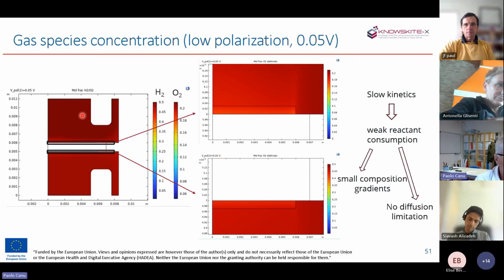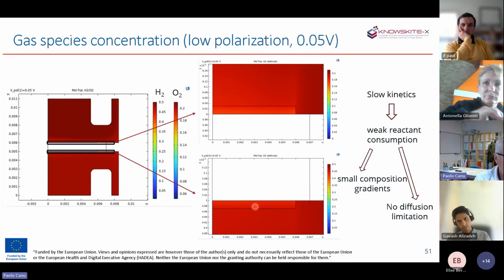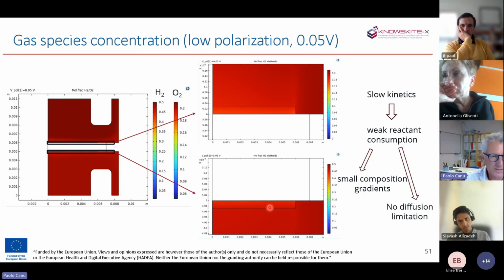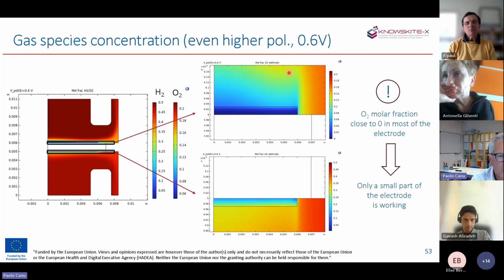The gas species, oxygen and hydrogen, within the electrodes are barely appreciable on this scale. So you need a magnification to see the electrode, and at low polarization, you see that the concentration, which is described by the color, of oxygen in the cathode and hydrogen in the anode, is almost uniform. So there are not significant gradients. But if you increase polarization to a very high polarization, then you will see that the oxygen starts decreasing from the free channel, approaching the surface. And if you enlarge the surface, you see that it's also going down to almost zero within the electrode.